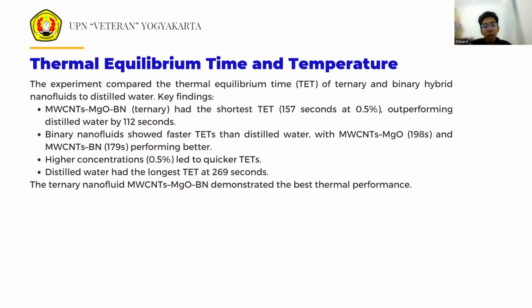The next one we have is thermal equilibrium time and temperature. The experiment evaluates the thermal equilibrium time of synthesized ternary and binary hybrid nanofluids using a fabricated FTET instrument, comparing them with distilled water as the base fluid. Number 1, ternary hybrid nanofluid exhibits the shortest TET, confirming superior thermal conductivity and heat transfer enhancement. At 0.5% volume concentration, it reached equilibrium in 157 seconds, 112 seconds faster than distilled water.